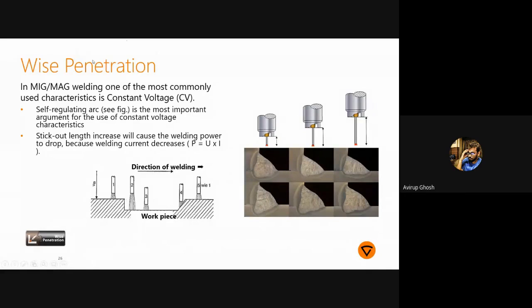Penetration is another one of the most vital sectors of discussion in welding. What happens when the stick out length changes? The stick out length is basically the distance between the contact tip and the job. It can shift during manual welding. We know a manual welder will not be able to keep his hand constant while welding along a long linear path. What happens when he has moved from 15 mm stick out to 30 to 40 mm stick out? The practical result of this situation is a decrease of penetration or lack of fusion.